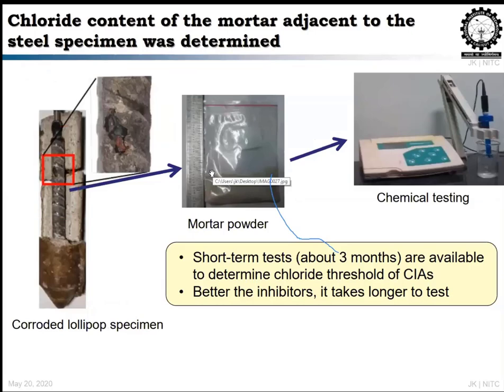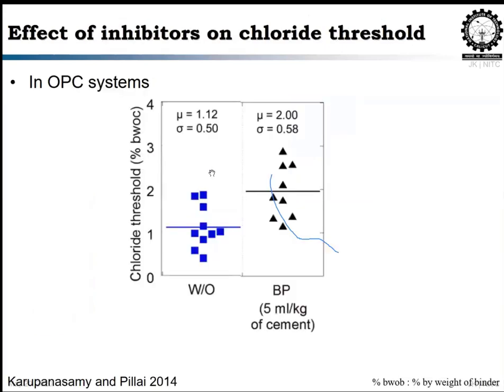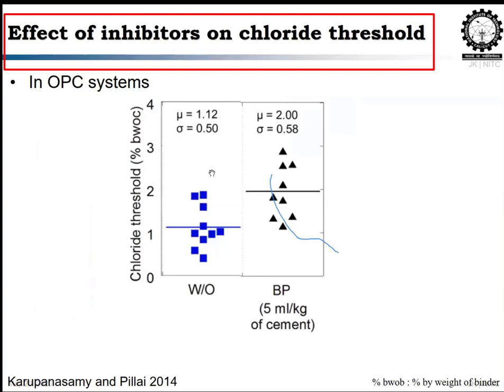By this we will find what happened at the steel surface, which is exactly replicating what will happen in your real structure. That is the purpose of this testing. With that, you can see I have compared chloride resistance or threshold value between the cementitious system which doesn't have an inhibitor and which has a bipolar inhibitor.